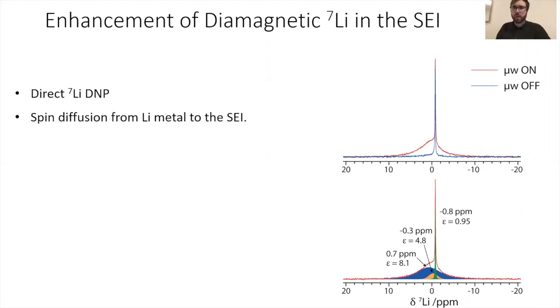Right, and skipping back a little bit, we're coming close to the end of time, but Marcel Levien asking, how far away from the metal phase can the lithium be to still get hyperpolarized by the irradiation of the metallic lithium? Do you want to answer that one, Katerina? That's something we're trying to find out. We'd like to know. To be determined. Again, it's very dependent on the mechanism. If it has to directly interact with the electrons, then that's one over r to the six type dependence. That has to be very close. But if there's spin diffusion, then that's a very different story, and it depends on the density of the appropriate spins, and that's also not very well known, but it will be an interesting factor to investigate, because, as I say, this is a heterogeneous structure and it's not a uniform spin density.